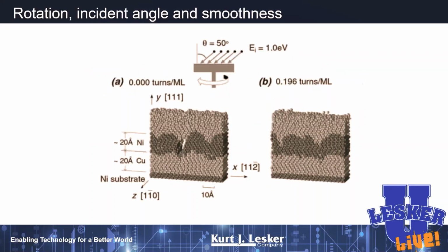Now, notice also that a lot of your substrate holders are going to have your substrate at some kind of angle relative to these incoming atoms. That is so that we can do what's called atomic level peening. If we had our atoms coming in normal to the substrate, generally speaking, they're going to stick wherever they land. They're not going to move around very much, and so you're going to end up with some voids in your film. Whereas if we have atoms coming in at an angle, each atom that comes in is going to peen, it's going to bonk into an existing atom and move it around a little bit. By doing that, we can have improved density in our films.